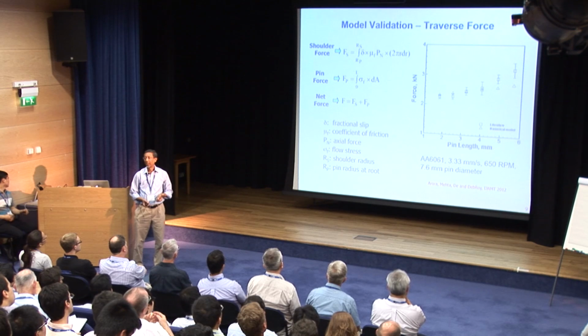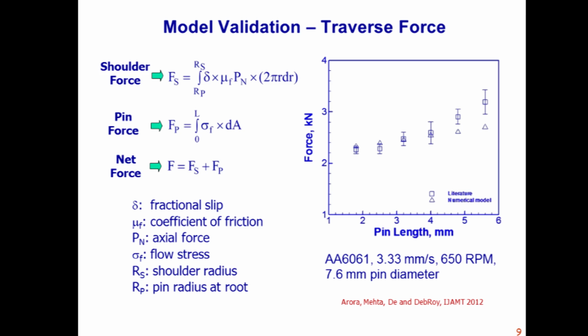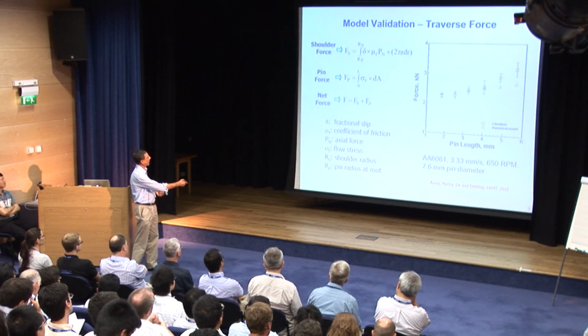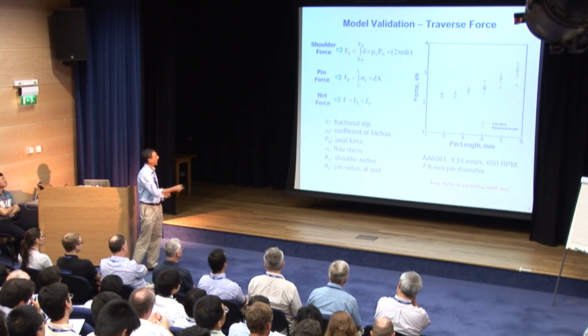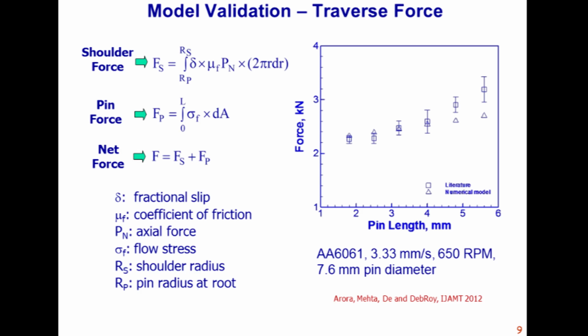Apart from velocity and temperature, we can actually measure the force on the tool as the tool moves around. So the traverse force can be computed, and then we can see how good those computations are by measuring it. You can measure it with a standard dynamometer or with a strain gauge or other possible techniques, and they seem to be predicting both the values and the trends reasonably well for different thickness of materials. All right? So temperature, velocity fields, traverse force.